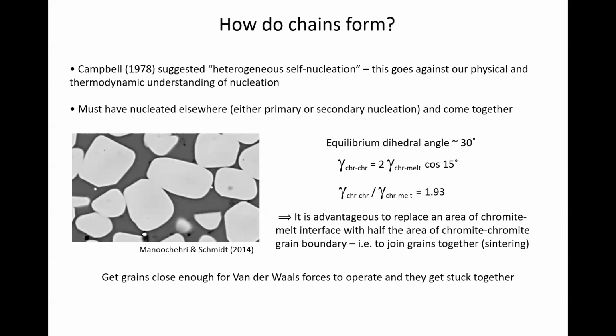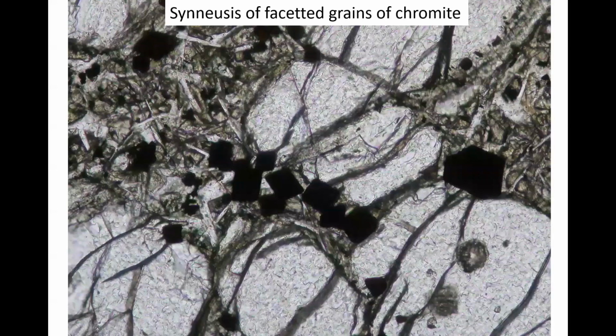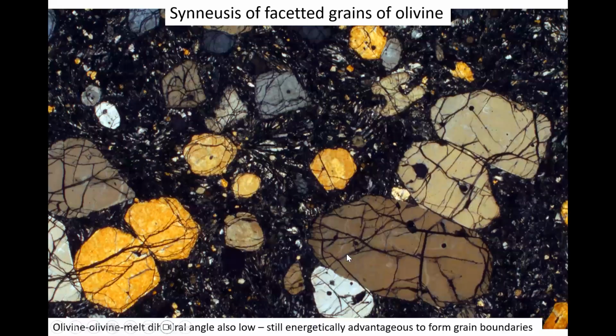Okay, so the synneusis model is that they're moving around because of magma flow, convection, whatever. When they get close enough to another grain, they'll come together and sinter and form a grain boundary, because that reduces the total energy of the system. So if we have synneusis of faceted grains of chromite, this is what we get. They are bound together on these 111 faces or 110 faces. They come together and form by synneusis.